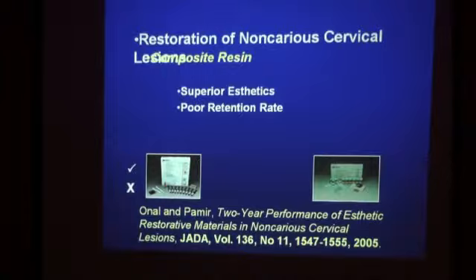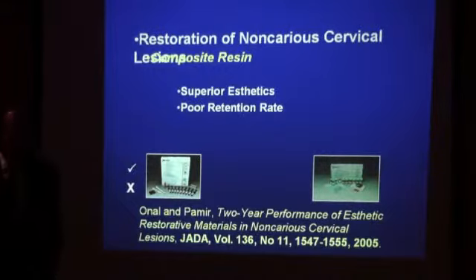And what they found with composite resin was that the composites delivered superior aesthetics. These were very beautiful restorations. They had nice contour. They had nice polish. They retained their polish for the full 2-year duration. But the problem with the composites was in their retention rate. These authors found that after 2 years, 1/3 of the composites were lost in the noncarious cervical lesions. 1/3! That's totally unacceptable.